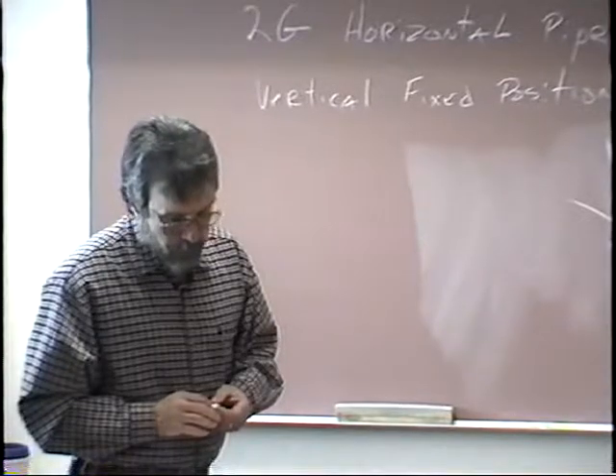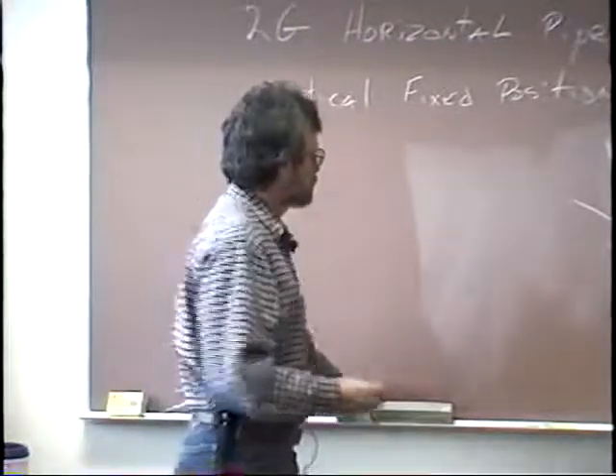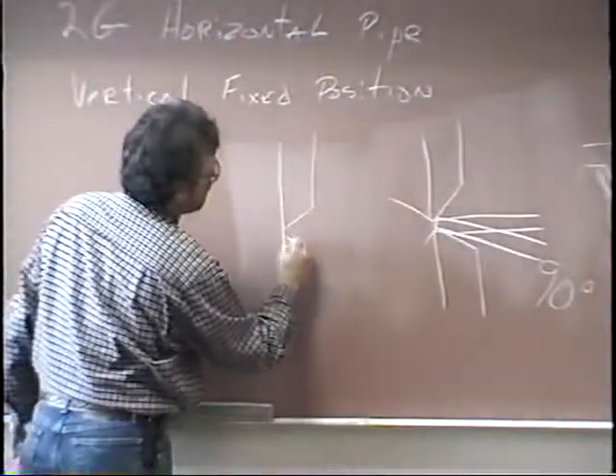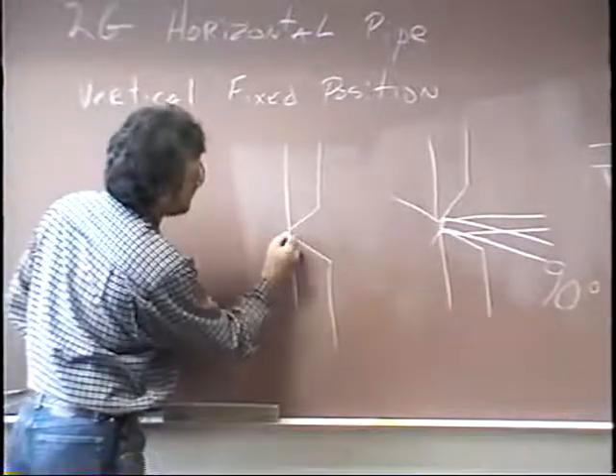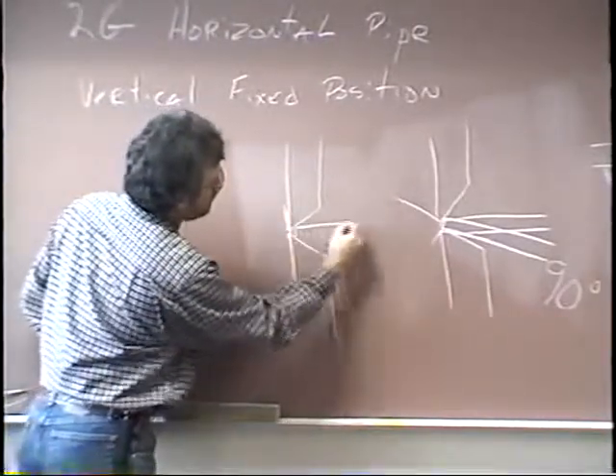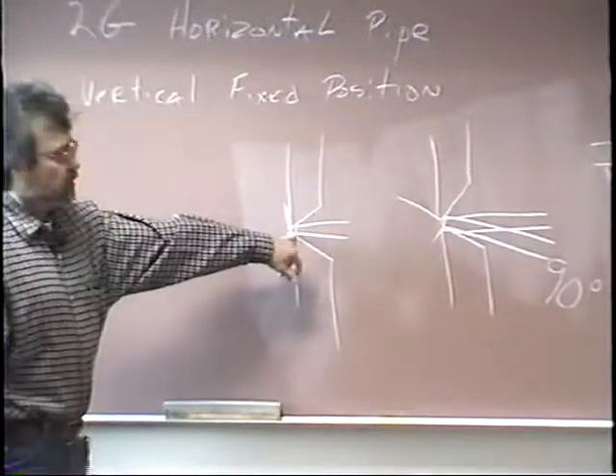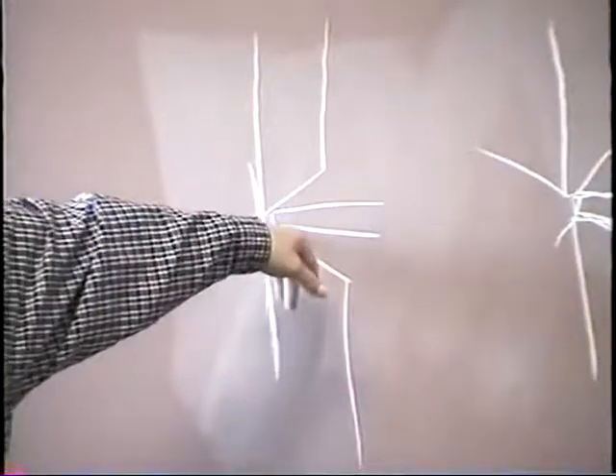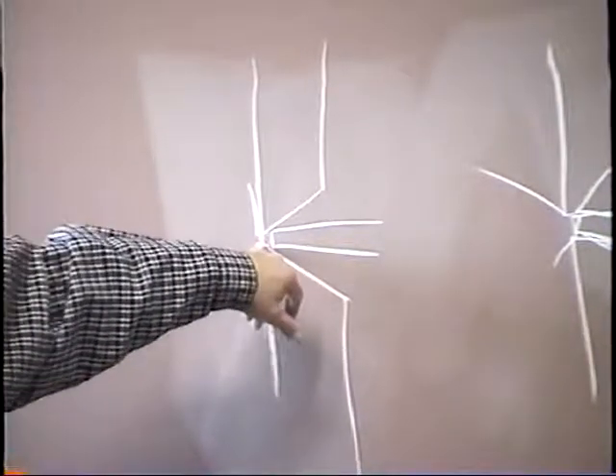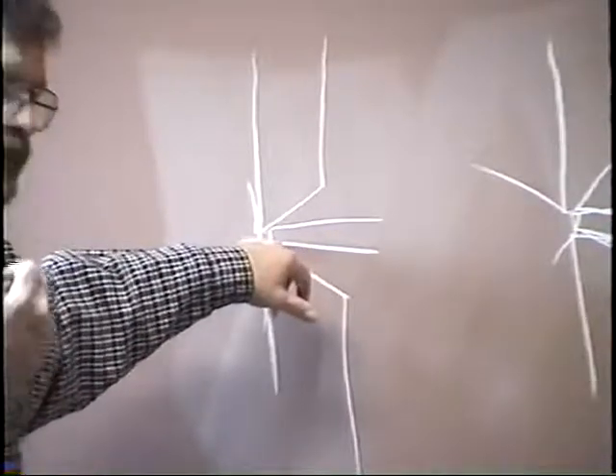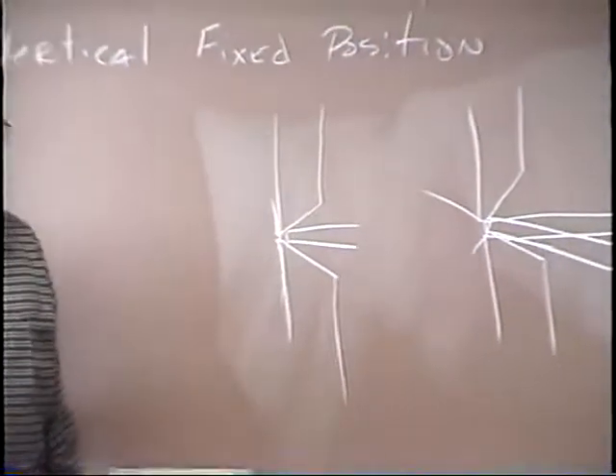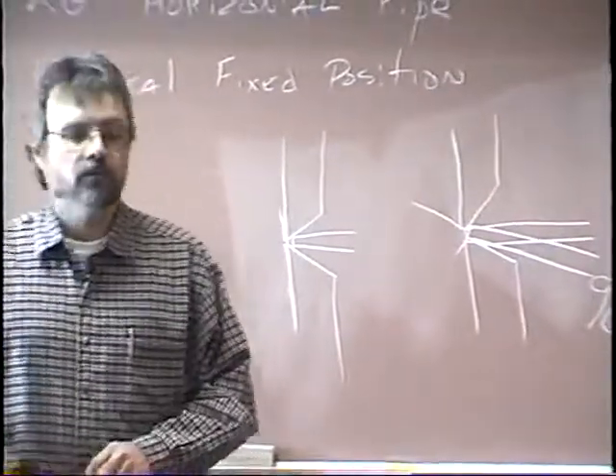If you look at the figure 9.4, it says arc length, and look at the relationship of the rod to the land. He's got a little bit of a land here, and that welding electrode is held just off the land. You see, so this keeps you from blowing out that land and getting internal undercut. The author suggests holding it off 1/32 of an inch, and that's just about right. A lot of times I'll say just go ahead and rest it right on the outside face of the land. If you can hold it on the outside face of the land, you usually get good penetration. It's just when you try to shove it in too far that you can have internal undercut. Now, does everybody know what a land is? I've described that. It's properly called your root face, but a shorthand term for it is land.